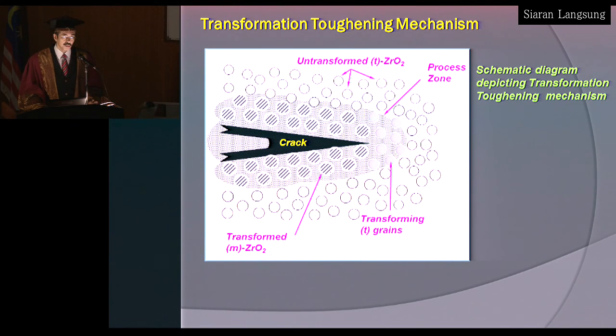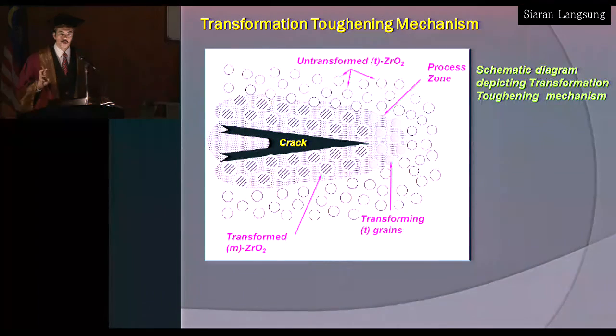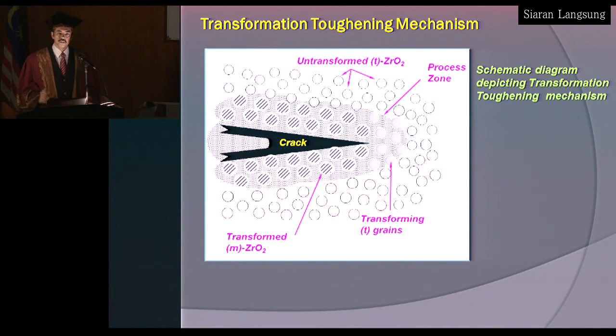Okay, as I mentioned just now about the toughening mechanism, what happens is that when there is a crack trying to propagate through the material, the surrounding tetragonal structure will absorb the stress, and energy needs to be used to do work. So as a result, phase transformation takes place in the vicinity of the propagating crack. And as this progresses, as more stress is induced by external loading, forcing the crack through the material, you have transformation taking place at the tip of the crack into the monoclinic form. Now, because the bulk of the material is still in tetragonal, there is a back stress imposed onto the wake of the crack. And this results in closure of the crack.